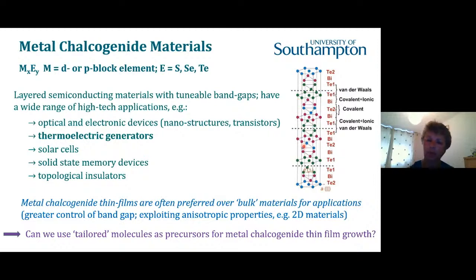This is a portion of the crystal structure of bismuth telluride, Bi2Te3. And what we can see here, without getting too much into the detail of the structure, essentially these are layered semiconducting materials. The layering is important because we have layers of tellurium separated by a gap and then more tellurium. And these are a little bit like the layers in graphite, where there are individual layers all stacked up on top of each other and weak van der Waals forces that hold the layers together. What that means is that these materials are highly anisotropic, so their properties are very different depending on the direction of the material that you're investigating as a result of this structure.